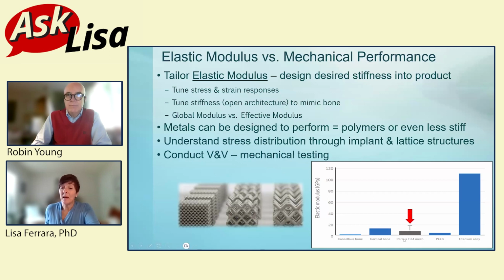But as you can see here, depending on how large that porosity is, you can be lower than PEEK, you can be slightly greater than PEEK, versus conventional bulk titanium alloy, as you see here. And you're even less than cortical bone. You can get closer to cancellous bone. Now, I'm going to caution everybody. Folks are coming out with implants that have a lattice structure that looks like trabecular bone and making that claim. And that's fine if they prove that it is. But there you go. Trabecular bone, cancellous bone, is anisotropic, meaning it's not uniform. Are you really mimicking bone?